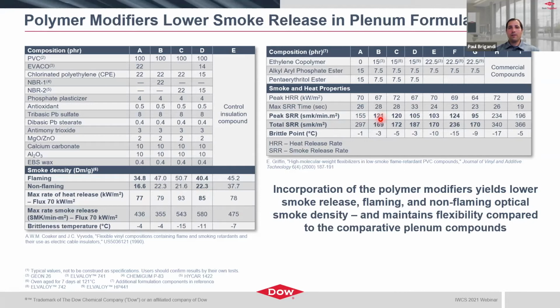And in the second case, we have Griffin and her team looking at these materials, again in a plenum cable application compared to some commercial materials. What we show here is a lower peak smoke release rate compared to the commercial control specifically, as well as a lower total smoke release rate. And again, with the incorporation of these materials, we are able to permanently plasticize the material so they maintain their flexibility at low temperatures, which we will talk about in subsequent slides. The low temperature brittleness temperature in each of the respective cases is shown.